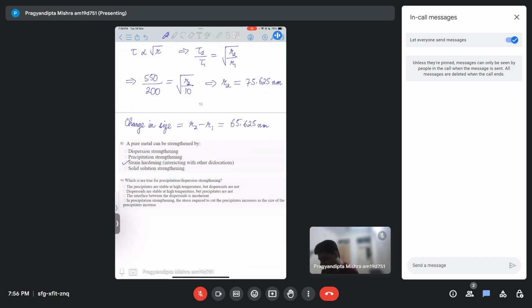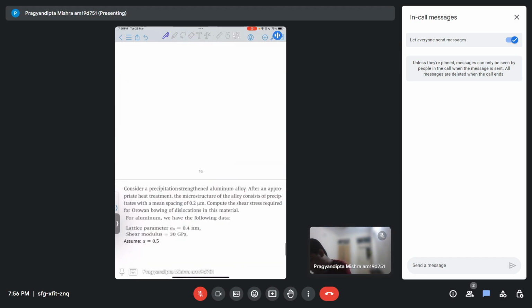Then which are true for precipitation or dispersion strengthening? The precipitates are stable at high temperature but dispersoids are not. That is wrong. Dispersoids are stable at high temperature but precipitates are not. That is correct. The interface of dispersoids is incoherent. That is correct. In precipitate strengthening, the stress required to cut the precipitate increases as the size of the precipitate increases. That is true, right? Because tau is directly proportional to root of R. So as root R increases, the stress required to cut the precipitate would also increase.